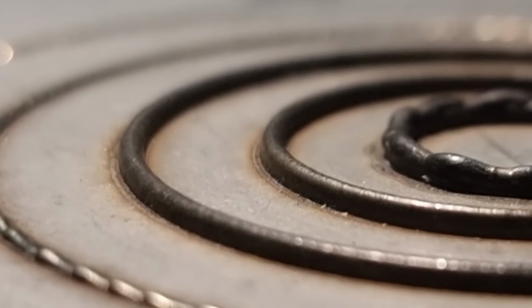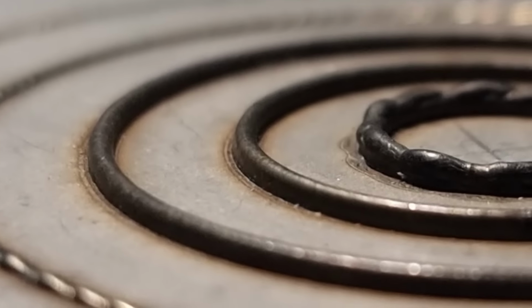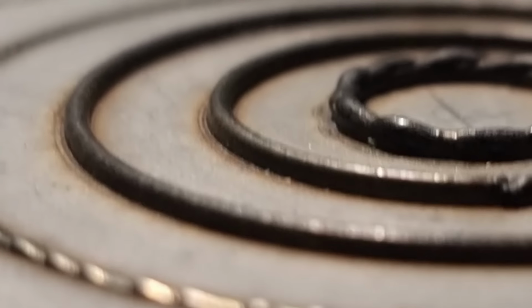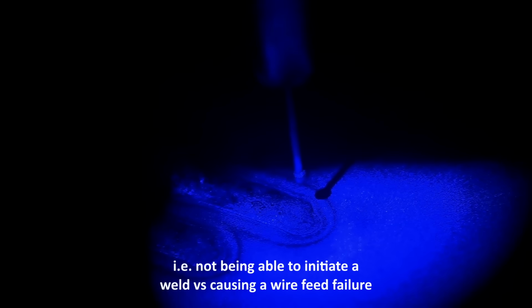To keep the print seamless, I had favoured a finer wire and therefore a lower volume of material, intended to be offset by a faster print speed. But this created a lot of issues as it was particularly susceptible to reflections, which meant initiating the weld was a delicate balance between too much or too little. By this stage, I was implementing a method to rapidly advance the wire when the continuity between itself and the substrate broke.